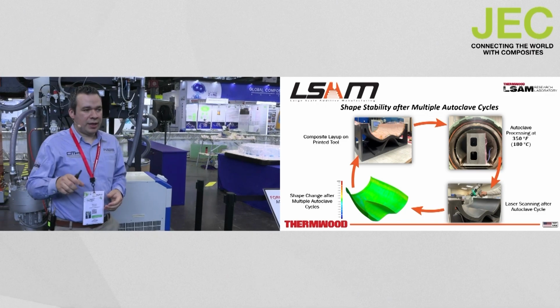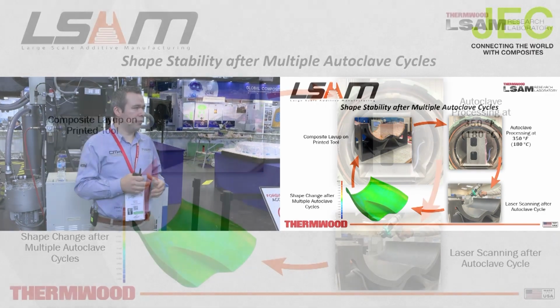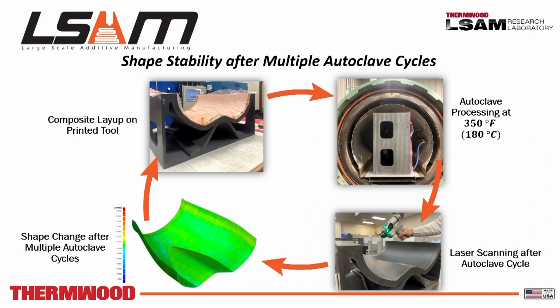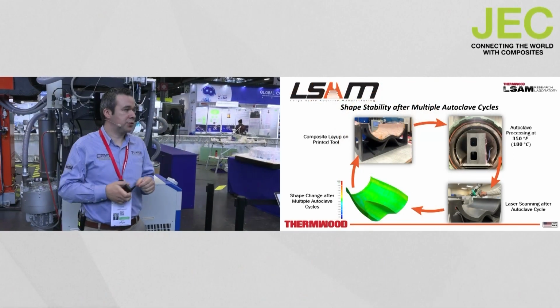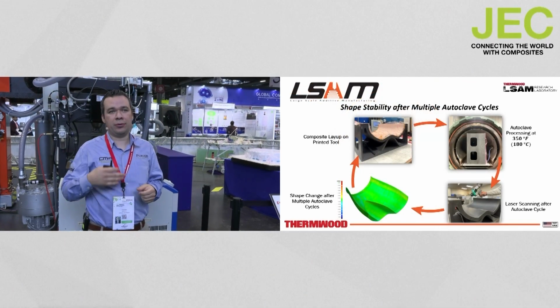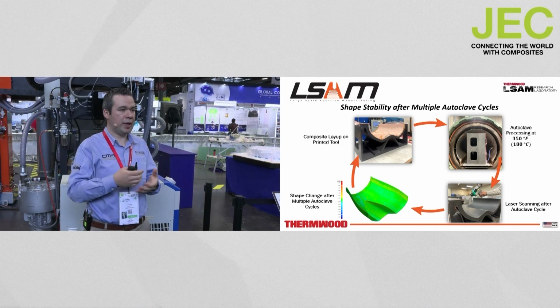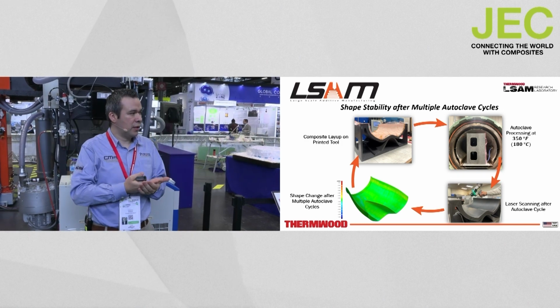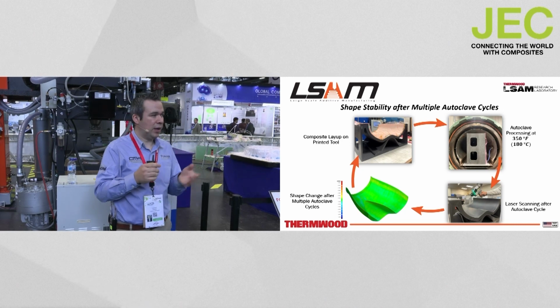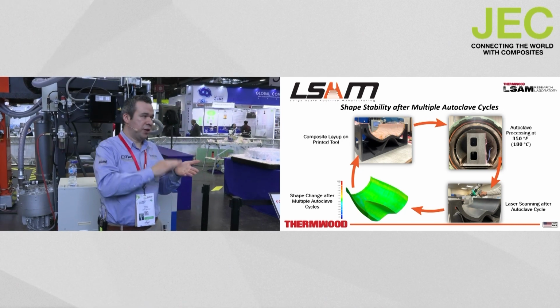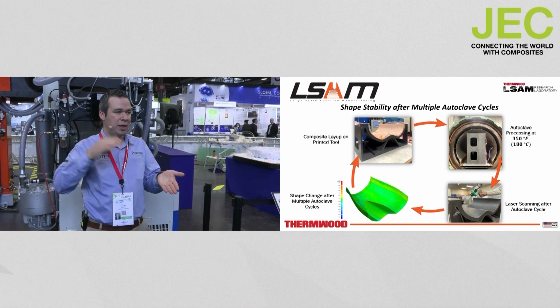Now, we also did a systematic study of the shape stability of this tool after multiple cycles. You can see in the first image on the upper left corner, we did a layup for a prepreg system that is cured at 180 Celsius in an autoclave. So we did multiple cycles in the autoclave, and then after each autoclave cycle, we laser scanned the surface to perform a deviation analysis. So you can see there in the bottom left corner a plot of the deviation between the shape at the beginning of the study and the shape after multiple cycles.